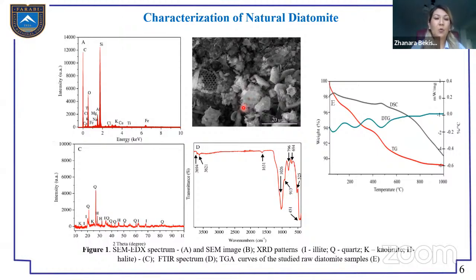And this phenomenon was confirmed by X-ray diffraction. The main minerals in the diatomite are quartz, kaolinite, illite, and halite. And we can see the peaks of the diatom frustules. It is amorphous quartz from 20 to 35 degrees. The main functional groups are the vibrations of OH and HOH, COC, CO aluminum bending. And with the changes of temperature, the mass loss equals 10%. This is water bonded on the surface and bonded with the silanol groups.